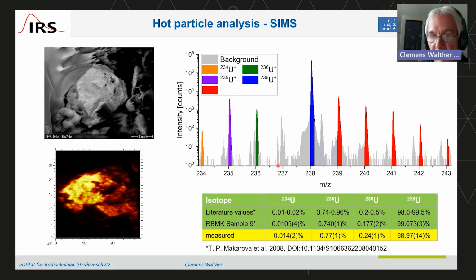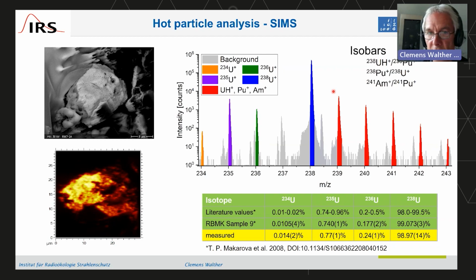You see that particle again, you see the uranium isotopes. This is uranium-238. This is uranium-235. You can tell that you have a uranium ratio that is slightly different from natural uranium, so that was enriched. Then you see uranium-236 that is not present in natural uranium, so you know it spent quite a while in the reactor. And these red lines here are probably not uranium, so you suspect that might be plutonium, also a sign that the sample came out of a nuclear reactor. But it might be plutonium, it might also be just an artifact of your mass spectrometry measurements. That is uranium hydride: uranium-238 plus mass 1 of the hydrogen gives you also 239, and that is hard to discriminate.